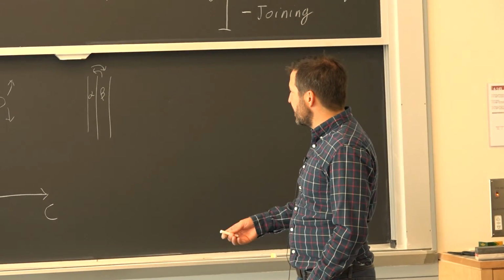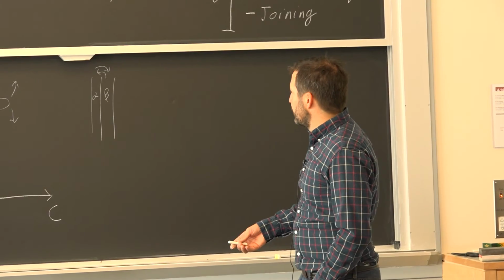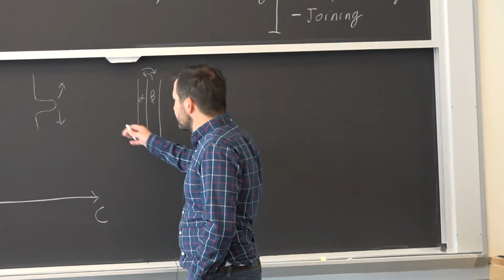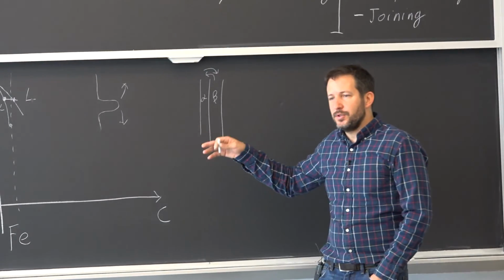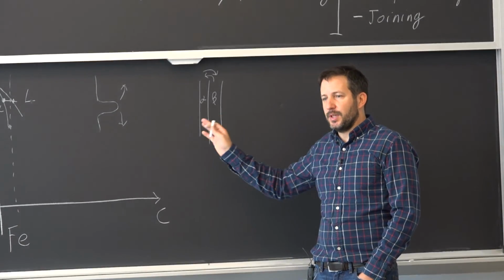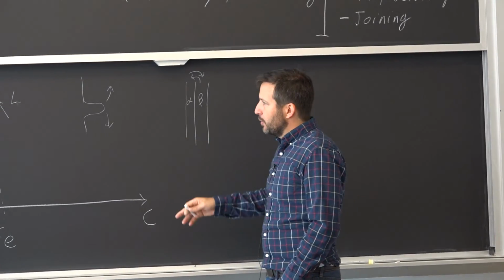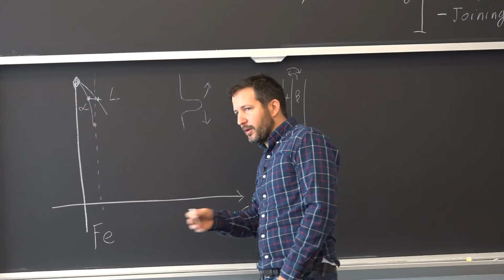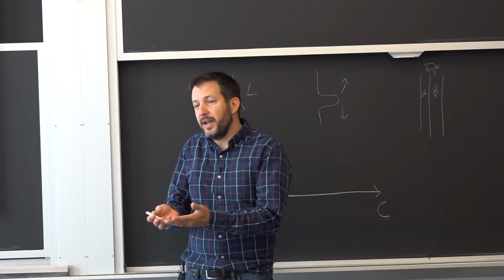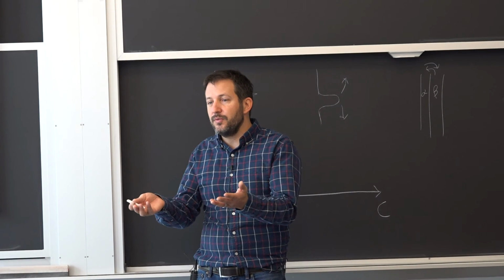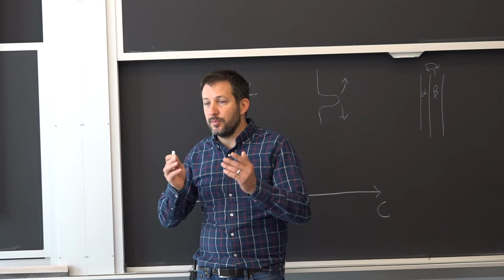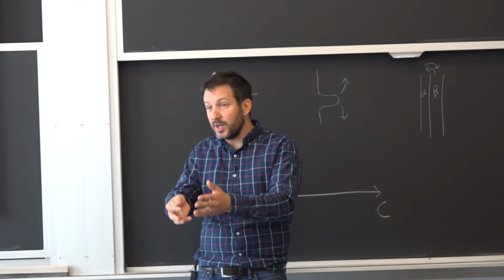Well, the first thing that's going to happen when you heat it up, it does sort of mix in by diffusion a little bit. So everything at higher temperature, we're going to go through that. You get grain growth, you get certain boundaries to disappear, you get your chemical gradient to disappear, because now you have those two phases, and it's not the equilibrium. It's just the way you did because you did it quickly.